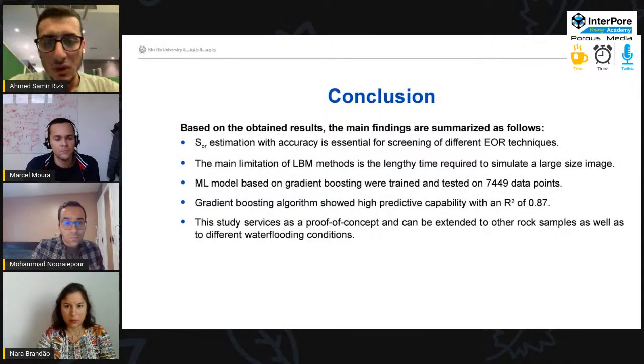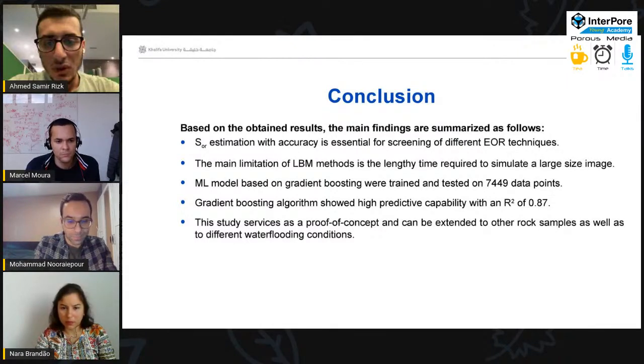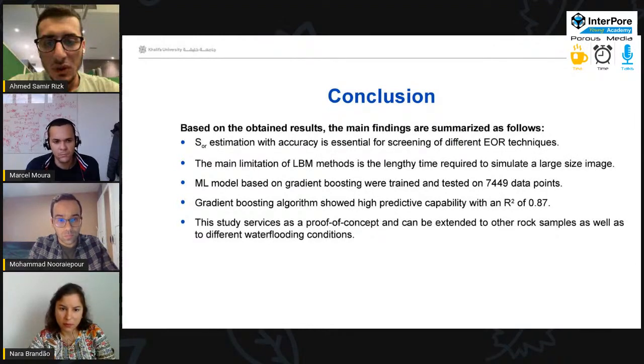Here we come to the conclusion. Based on these results, we know that the SOR estimation is very important, and we need an accurate and fast way to estimate it, because it can be used in screening different EOR techniques. Because of the limitation of current simulation techniques like Lattice Boltzmann, which require a huge amount of time or resources to simulate an image, we developed a machine learning model that was trained and tested based on 7,449 data points. The gradient boost algorithm showed a high predictive capability with R square of 0.87, and finally this study serves as a proof of concept, and it can be extended to other rock samples as well as to different water flooding conditions.